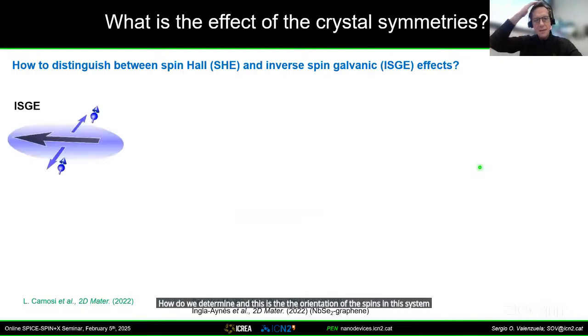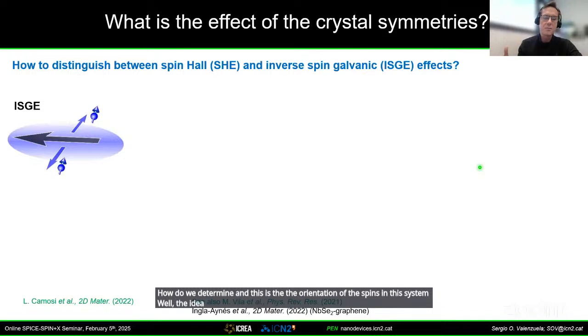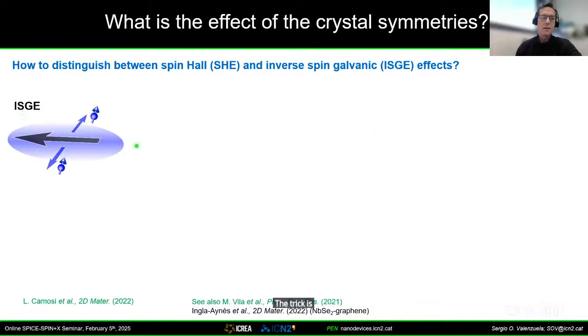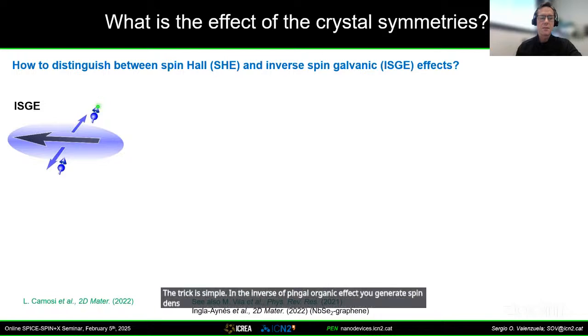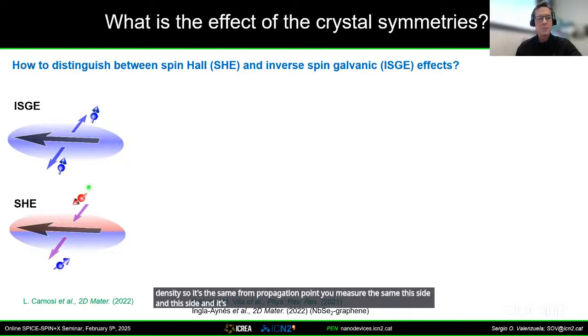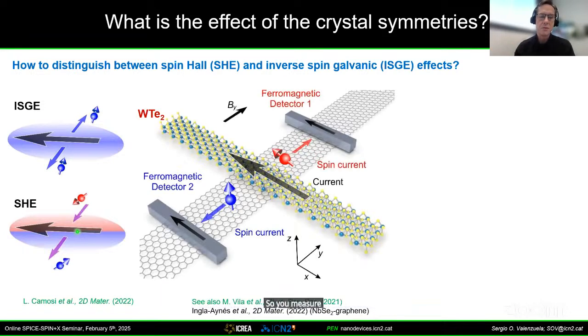So how do we determine the orientation of the spins in this system? Well, the idea is kind of simple. The same happens with the spin galvanic effect. So we need to at least determine what is a spin Hall effect and what is inverse spin galvanic effect. The trick is simple. In the inverse spin galvanic effect, you generate a spin density. So it's the same from the propagation point: you measure the same on this side and this side. In the spin Hall effect, you generate a spin current, so you expect spin accumulation that is opposite on this side and that side. So you measure on both sides. That's what you do. And in this situation, you will see something different here and here. If it is the same, then it's only an inverse spin galvanic effect.